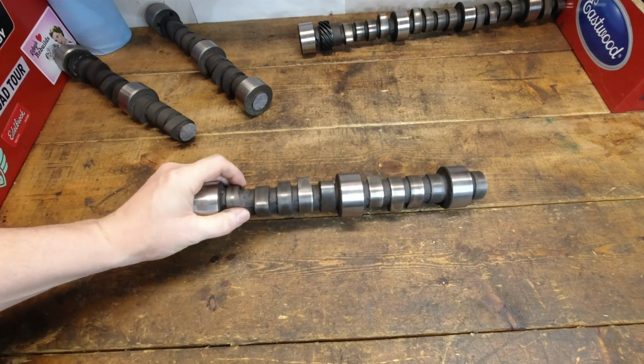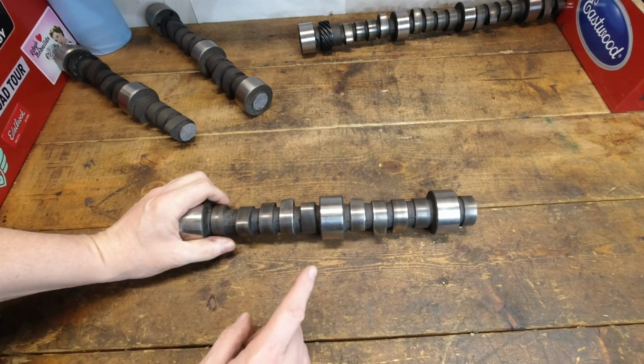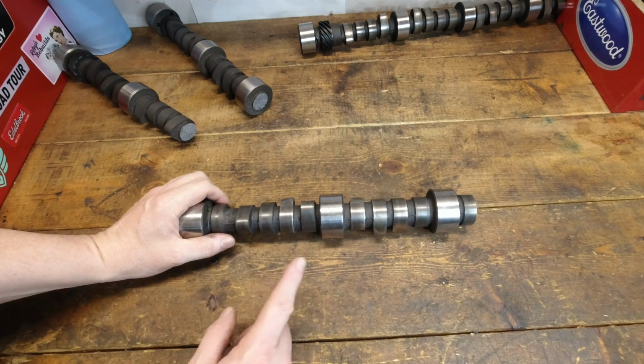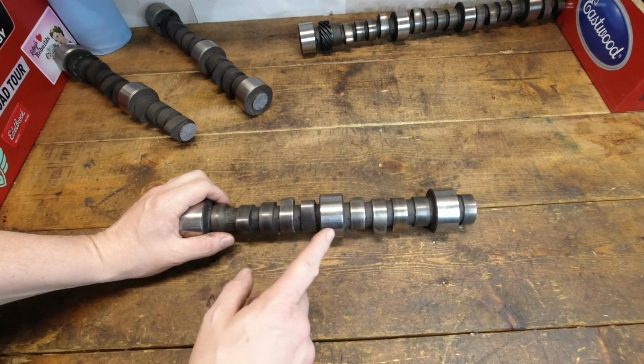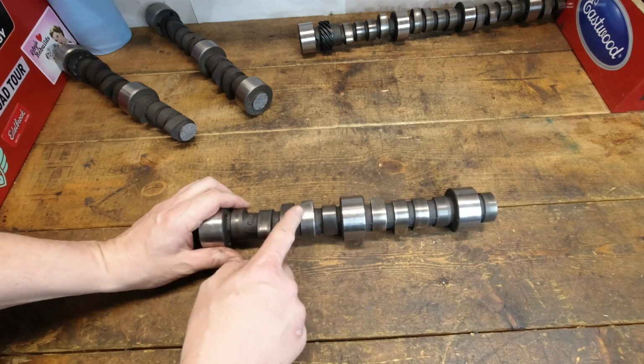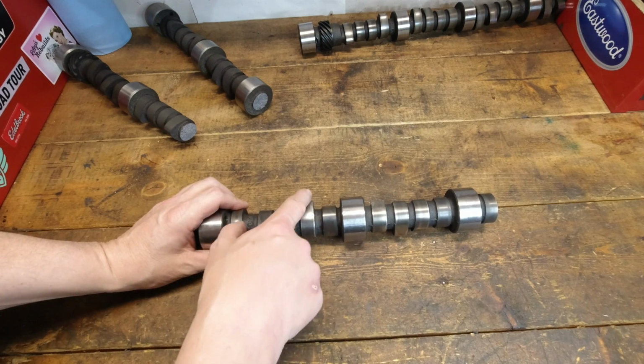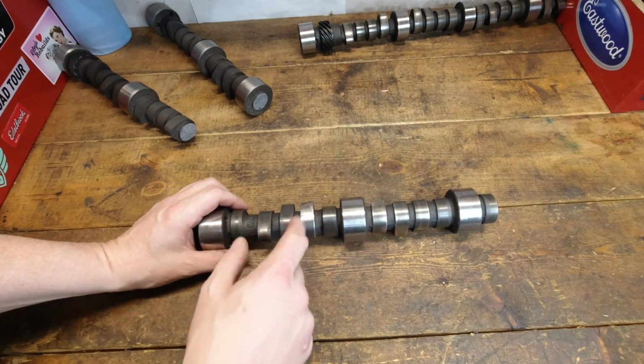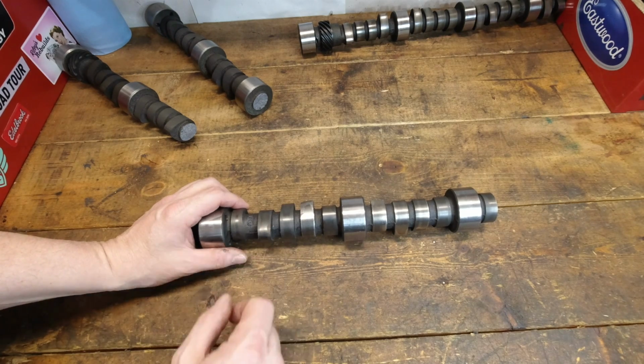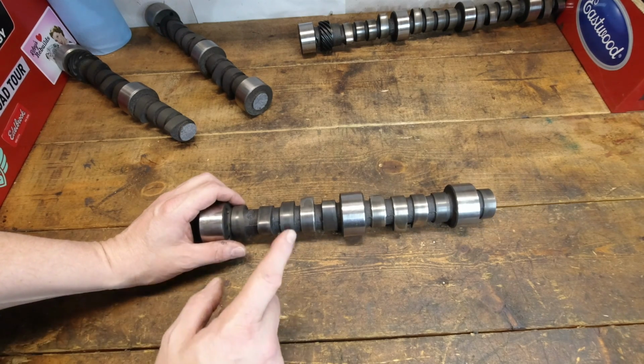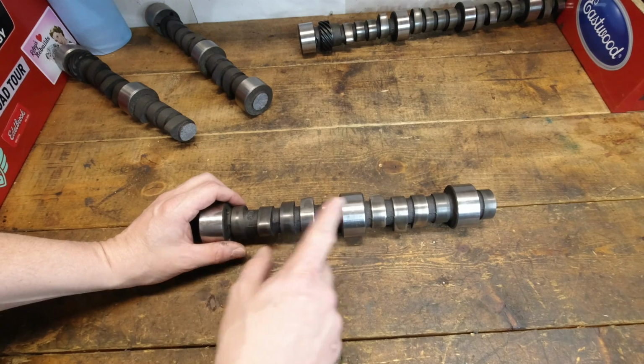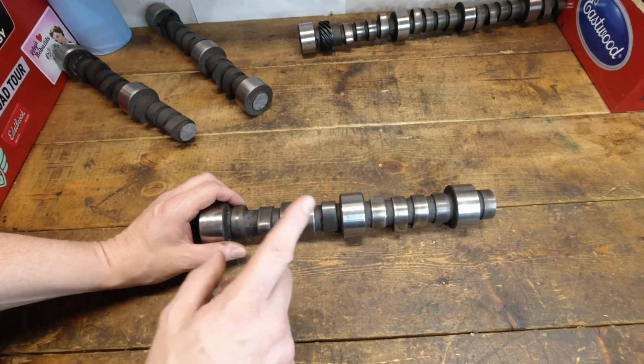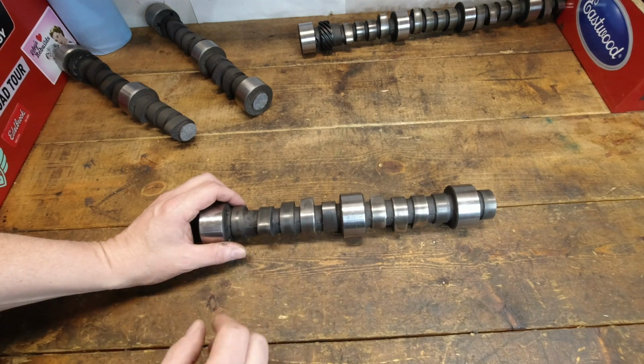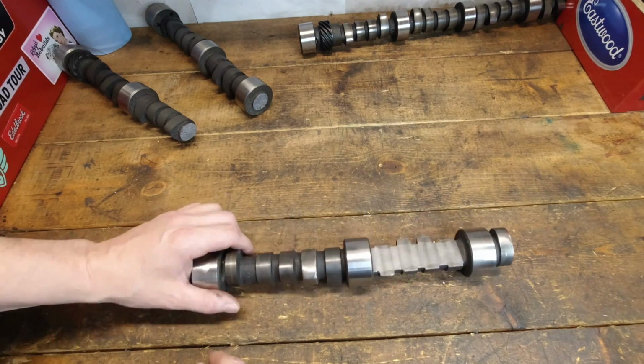Now let's talk about hardening and these camshafts. Now, this was a used camshaft. It failed, and what I did is I had it cut down so we could look and see the heat treating depth in it. You look and see that lobe there, it is clearly worn off. It's got one hell of a taper to it. I think that's a little excessive, but the point is even in a camshaft that failed, we can still look to see how deep the heat treating was, and that's what I want to show you today.